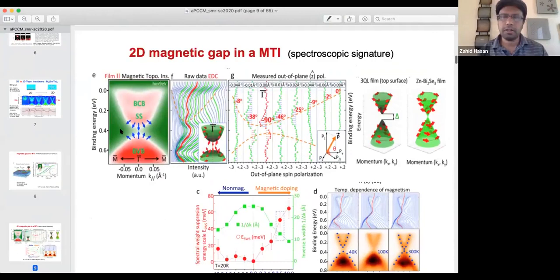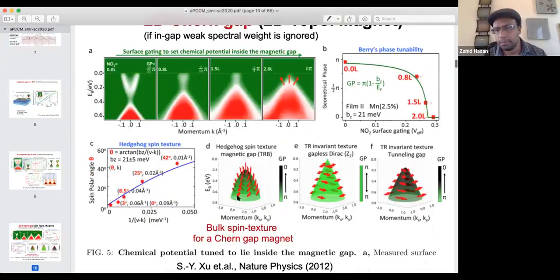Yeah, this is a spin-resolved ARPES. So we're mapping momentum, energy, and spin polarization. And we are only considering relative polarization. We're not measuring absolute polarization. To map whether the band structure has Berry phase, you just need to know the relative polarization. You don't have to know the absolute. So although spin ARPES by itself will not tell you the absolute polarization of your Fermi surface or band, for topological purposes, only the relative matters. If polarization is in this direction, the magnitude doesn't matter, only whether it's opposite to that or not. So in mapping this type of texture, I only care about the relative polarization. I don't care about magnitude and other things.